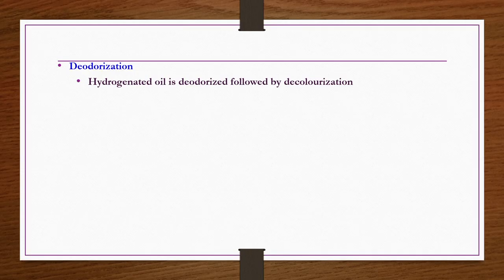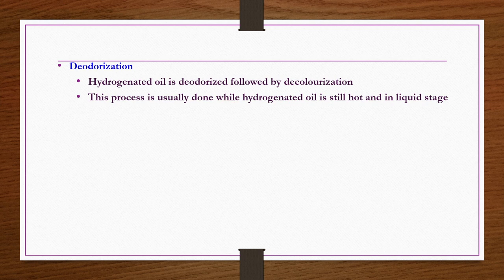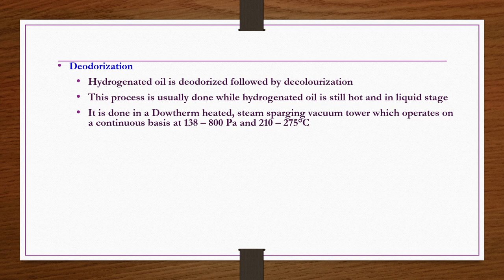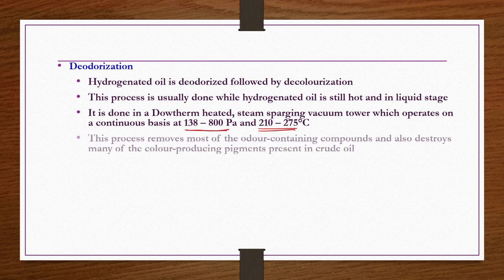Once the hydrogenation of oil is done, the saturation degree has increased or the unsaturation degree has decreased. Still after that you may need to do some processing, that is deodorization or decolorization, that we see now. Hydrogenated oil is deodorized followed by decolorization. This process is usually done while the hydrogenated oil is still hot and in liquid stage. It is done in a Dowtherm heated steam sparging vacuum tower, which operates on a continuous basis at 138 to 800 pascals and 210 to 275 degrees centigrade.